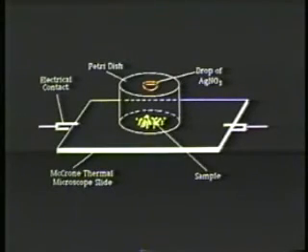And I'd like to show you just a simple experiment that my student did to convince me that this reaction was taking place, because I really was not a believer at first. And so what she did was simply take some of the starting materials, the starting co-crystal, that is the diacid co-crystal, and she put it on a heated microscope slide. And over the top of the slide, she put an inverted Petri dish with a drop of silver nitrate. And she decided she could do a silver chloride test this way, because if that nucleophilic substitution reaction was taking place, then one of the byproducts is HCl.